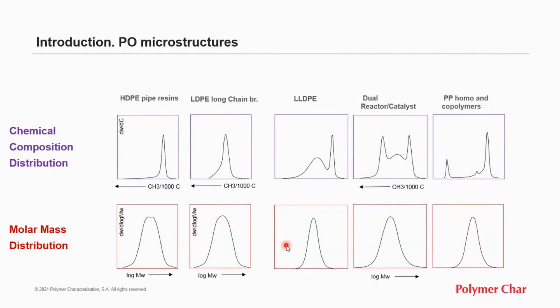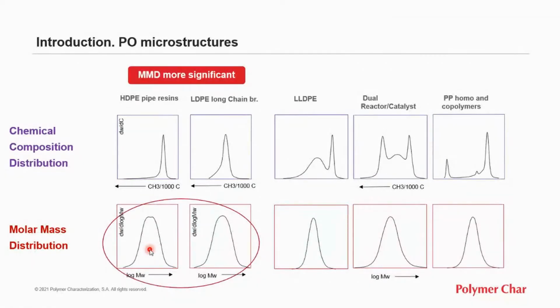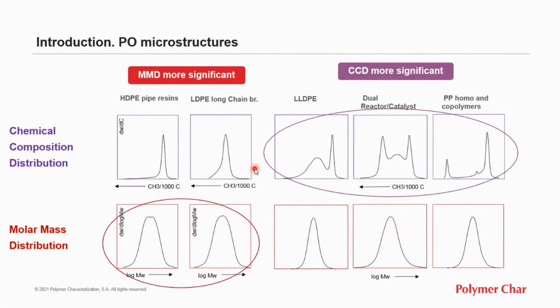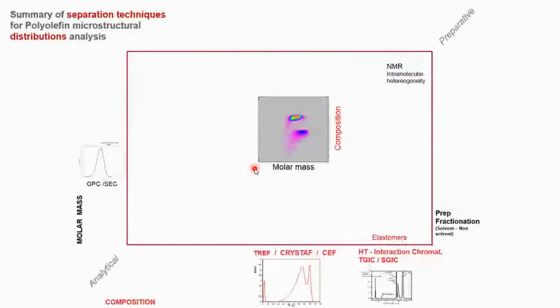So distributions are key. Polyolefin microstructure can therefore be characterized basically by both a chemical composition distribution here or a molar mass distribution. For some polyolefin cases, high-density polyethylene, low-density polyethylene, homopolymers in general, the molar mass distribution is more significant, while the chemical composition distribution is either narrower or has no special features. While in other cases, it is the CCD, the chemical composition distribution, which is more significant and so more useful to identify products and to relate microstructure to the product properties.